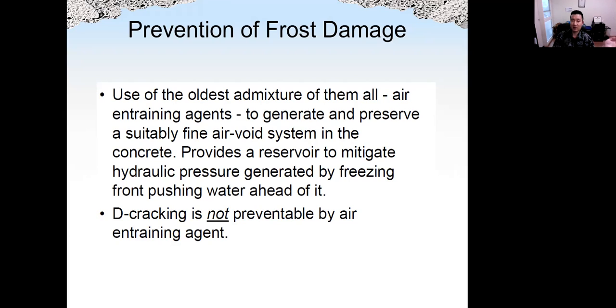And I think we discussed this when we talked about air entraining agent. But here it says D-cracking is not preventable by air entraining agent. Why is that the case? Remember, D-cracking is caused by frost damage of aggregate. If we introduce air entraining agent, that will introduce air bubbles in cement paste only. So D-cracking is frost damage of aggregate, and air entraining agent cannot prevent D-cracking.